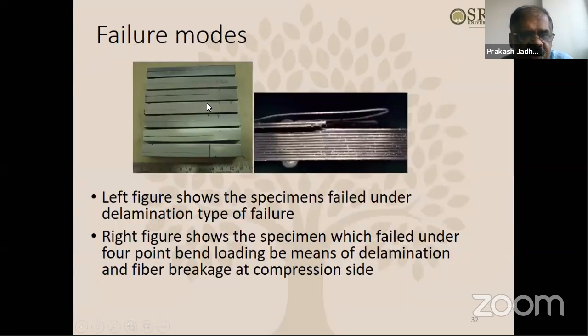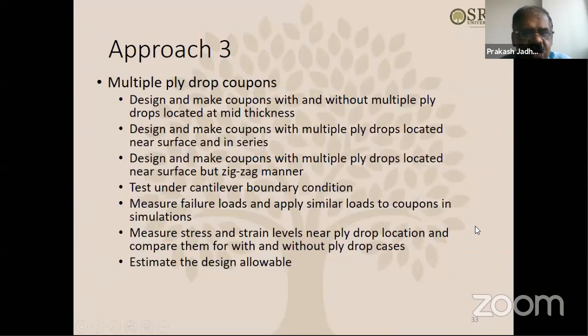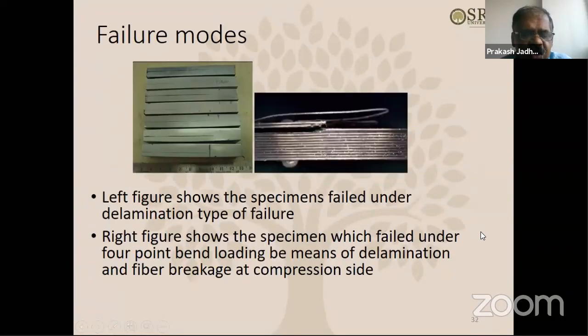So failure, of course, we saw that in short beam shear, the failure was basically directly a delamination type of failure. And in the earlier coupon that I showed you, where the ply drop is located near the surface, and we were subjecting it to tension or compression, that failure was something different. That failure was like fiber breakage at the compression side. Okay. So here the fiber was breaking at the compression side. Okay, so this was about the single ply drop and double ply drop coupon.